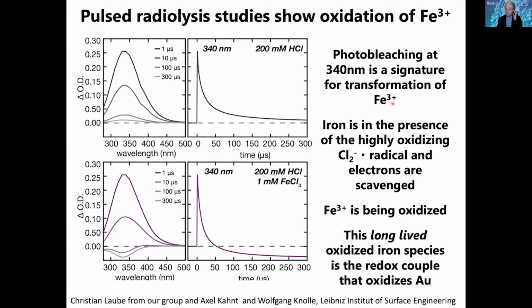The iron 3+ doesn't, and that's been one of the big mysteries for us. When I showed you the earlier work with the redox couples, for a while it was confusing to us because iron 3+ shouldn't have enough oxidation potential all by itself. But when it's placed into this higher oxidized iron species, it surely does.